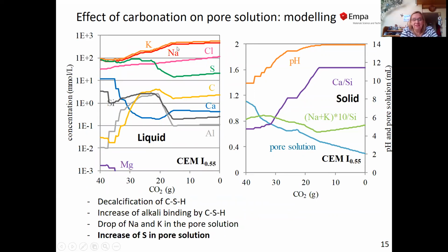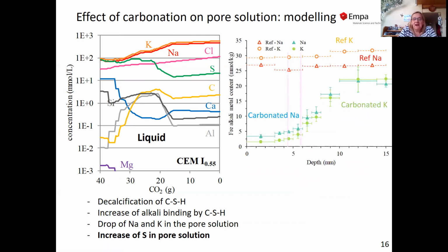If we look at the calculated liquid phase, this calculated increase of bound sodium and potassium translates into a lower concentration of alkalis in the pore solution. And the other thing we see is an increase of sulfate in the pore solution. Now, again, I want to compare it to the measured data, and we can see that this decrease we predict for potassium and sodium agrees with the decrease we have observed in the cold water extraction method, indicating that we are able to at least follow some of the things we have seen experimentally.